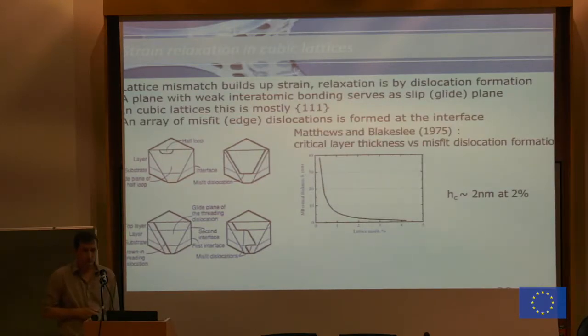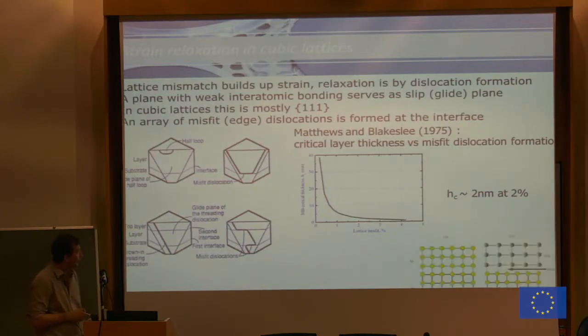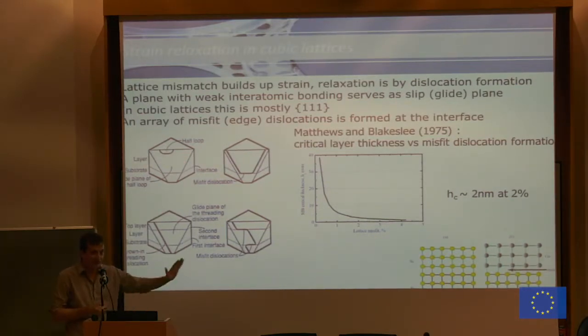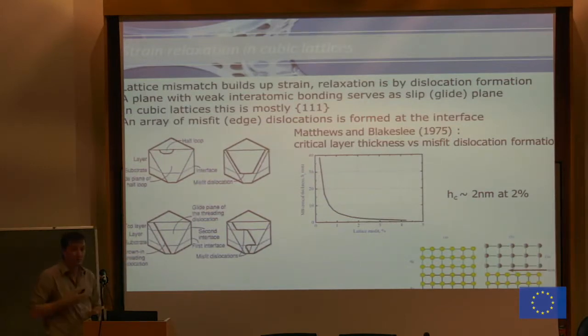So this plastic deformation happens in various ways. In cubic crystals, this is the model of Matthews and Blakeslee. It happens by dislocations sliding over what they call glide planes, which are planes where it is the easiest to slide. And there are whole theories on how this happens. It's really half loops of dislocations that slide across, and then you end up in this case.